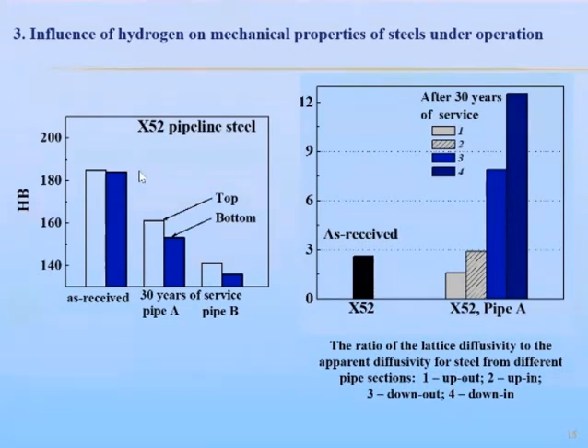And the intensification of damage in steels can be evidenced by the behavior of hydrogen in steels. Hydrogen extraction and permeation methods provide valuable information for assessment of the degree of in-service dissipated damaging. The hydrogen permeation method of Devanathan-Stachurski is used, taking into account that hydrogen in a metal is located mainly in defects, which are considered as hydrogen traps. Thus, using this method, lattice and apparent hydrogen diffusion coefficients can be determined, and the ratio is a measure of the trapping efficiency.